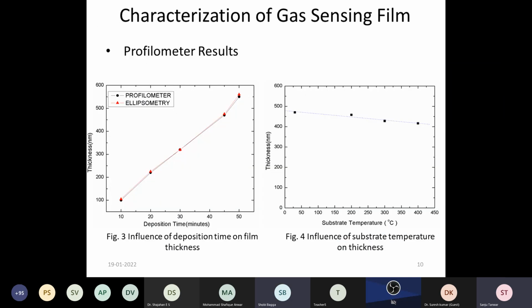So whenever we obtain the film, our first target is to check the thickness of the film, because we are varying the deposition time. Thickness of the film can be measured by different techniques. Here we have used profilometry as well as ellipsometry to determine the thickness of the film. We have confirmed by both techniques that there is an approximately linear relationship between the thickness and the deposition time. The black dots are the profilometer and the second one is the ellipsometer. I think most of you know about the profilometer.